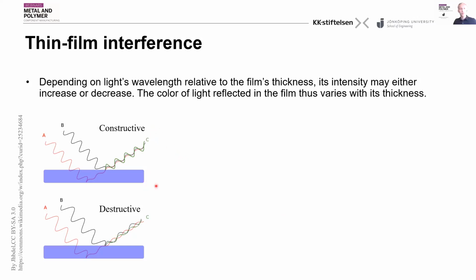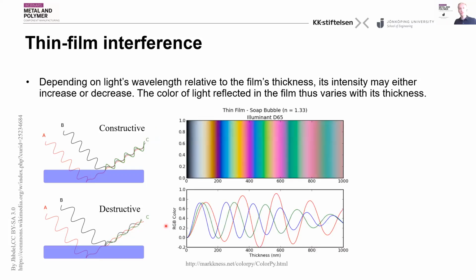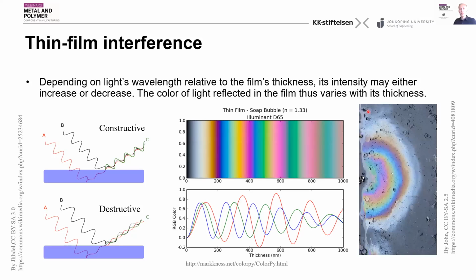So depending on the film's thickness, certain wavelengths or colors are reduced and certain other colors are emphasized. And this then causes a light spectrum which depends on the film's thickness. And this is what you actually see after you have done the color etching. Similar effects can be seen, you might be familiar with, for example, when a droplet of oil ends up on a wet surface, or on a soap bubble. Or you can even see it in the oxide films around a weld, for example.